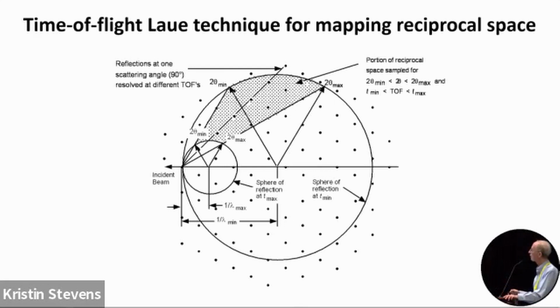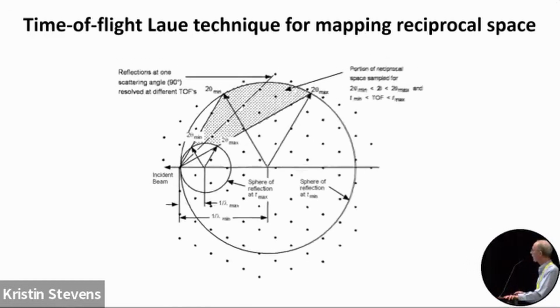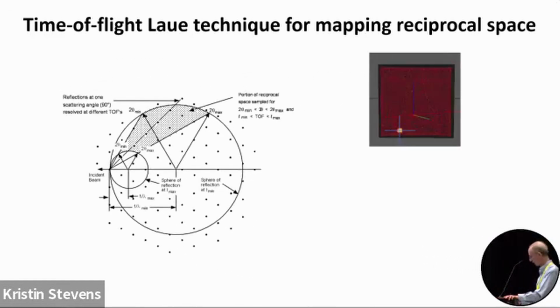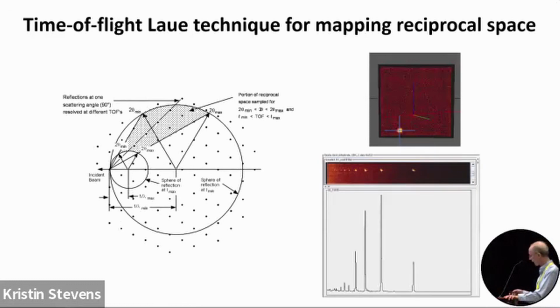And so if there's a point detector sitting out here at 90 degrees, we can actually sample this whole lattice line here. And with an area detector out here, we can sample a solid volume of reciprocal space during each pulse. So if we had an area detector, and here's what looks like a peak on the detector, but we've got a third dimension. And so here we see that one peak actually can be resolved into 8 or 10 peaks.